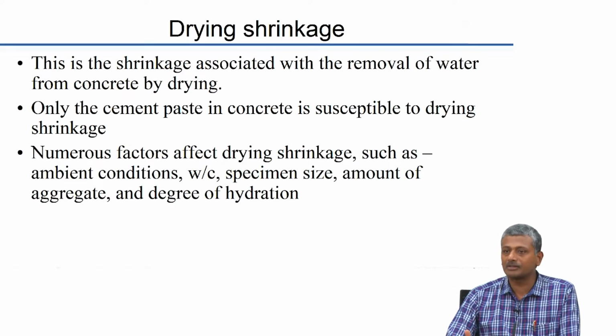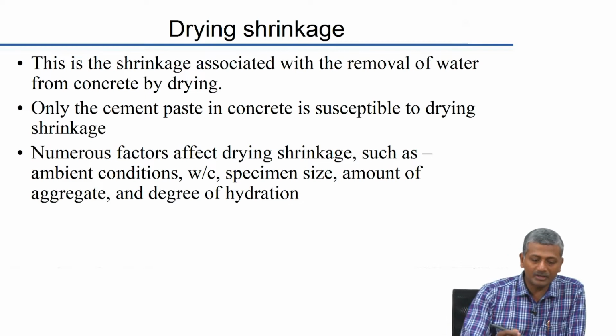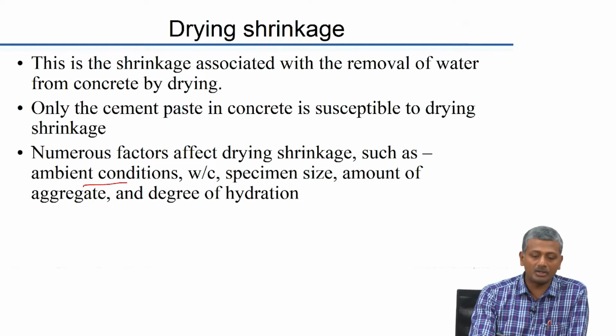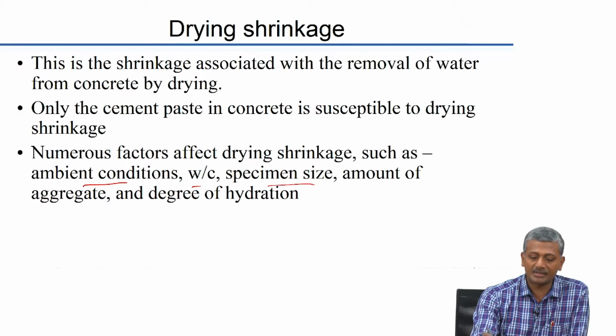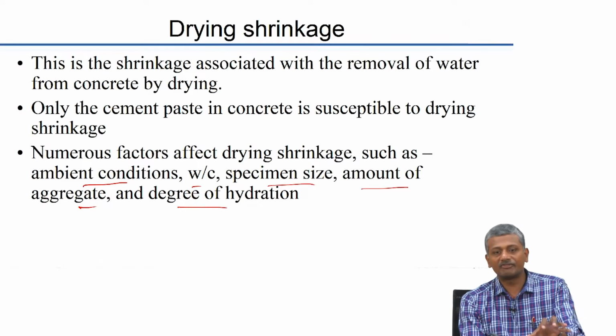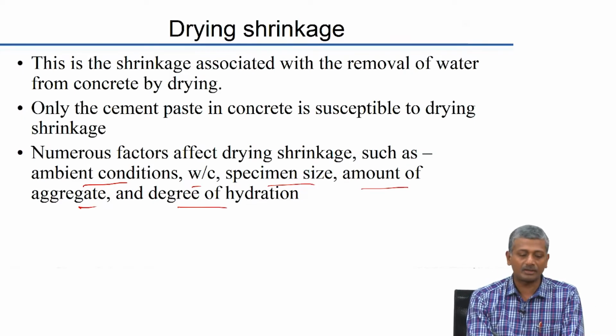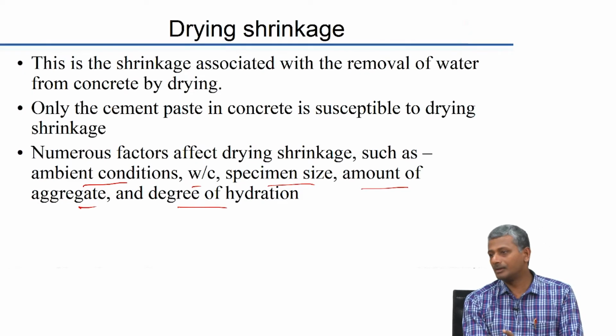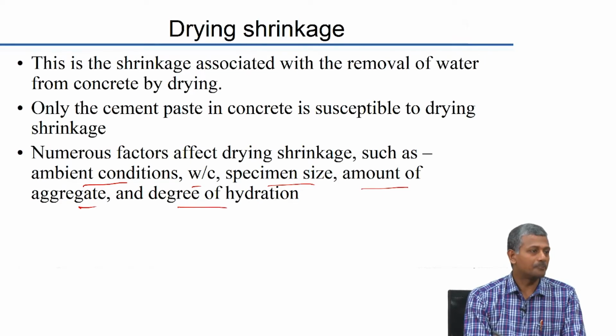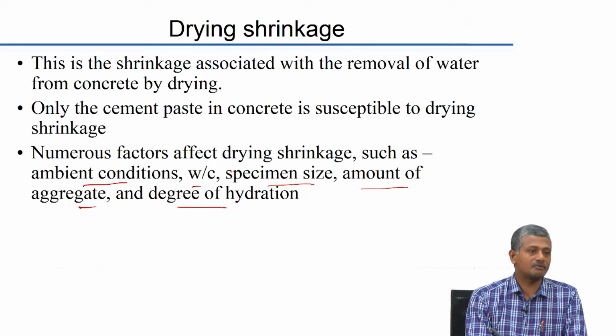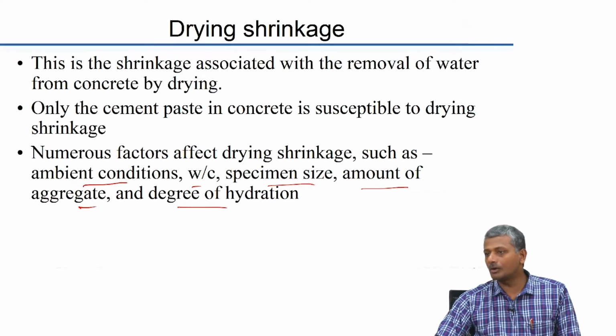And there are several factors which we have already seen before as to how they affect shrinkage, the ambient conditions, that is temperature and humidity, the water to cement ratio, specimen size, amount of aggregate and degree of hydration, right. All these affect creep in the same way that they affect shrinkage. So, for example, if I take the amount of aggregate, how does that affect shrinkage? More aggregate implies lesser shrinkage obviously. So, again the move towards this new mixed design philosophy where we optimize the aggregate content to minimize the pore volume, that is a good approach to take to reduce the overall shrinkage in your system.